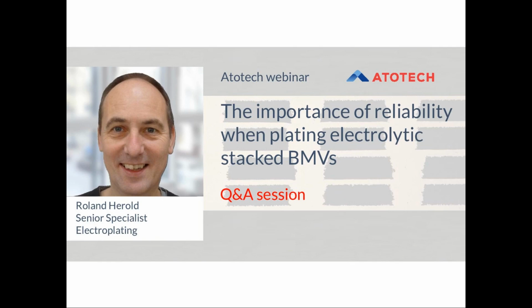So in general, when you apply a very strong reverse energy, of course, there's always a risk that you damage electroless copper layer, which is quite thin, especially inside the microvia. So that's clear. If the reverse charge is very high at the beginning of the plating process, then the electroless copper deposit might get damaged, and then you have voids.